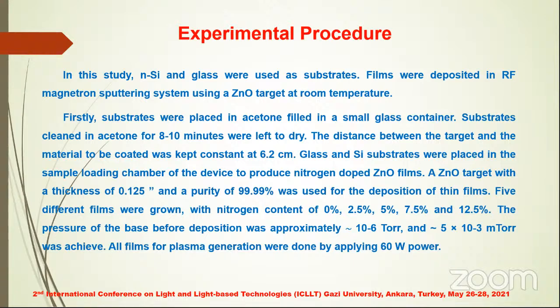Glass and silicon substrates were placed in the sample loading chamber of the device to produce nitrogen doped zinc oxide films. A zinc oxide target with a thickness of 0.125 and a purity of 99.99% was used for the deposition of thin films. Five different films were grown with nitrogen content of 0%, 2.5%, 5%, 7.5%, and 12.5%.